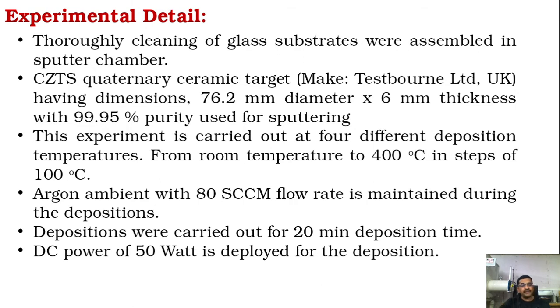These depositions were carried out in argon ambient. The flow rate of argon during the deposition is 80 SCCM. It is maintained throughout the depositions. Deposition time I kept constant for 20 minutes, and throughout the deposition I have used direct current, that is DC power of 50 watt.